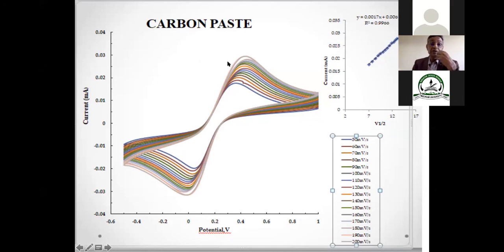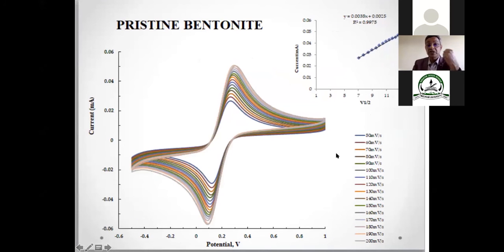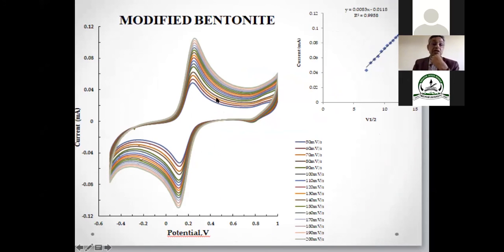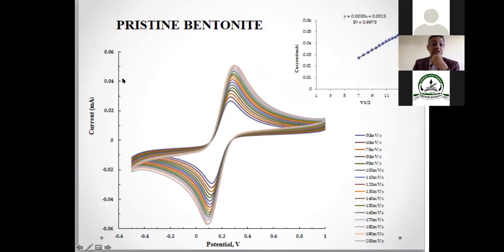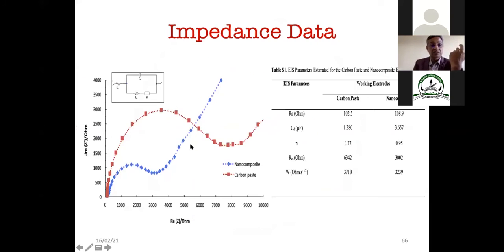So this is the carbon paste electrode data with the scan rate by which the electroactive surface area was calculated. This is the line for the Randles-Sevcik equation. This is the pristine bentonite. For the modified bentonite, you can see that the value of the current is much increased. It is almost 0.1, and in this case it was almost half of this, 0.05 or 0.06. It is almost double the value.